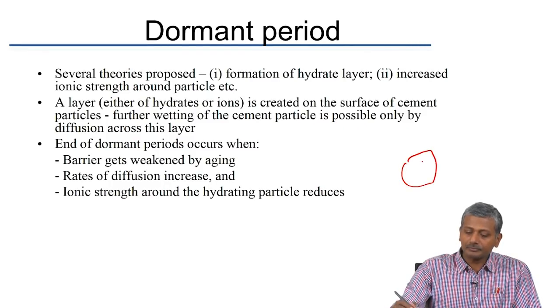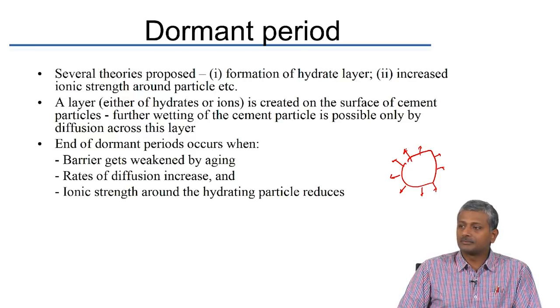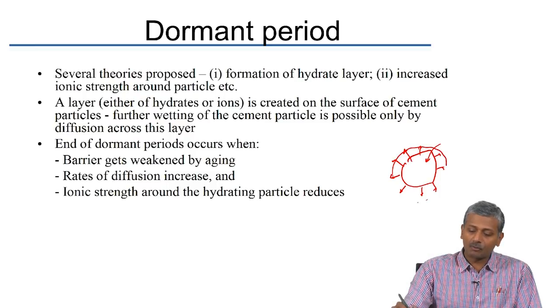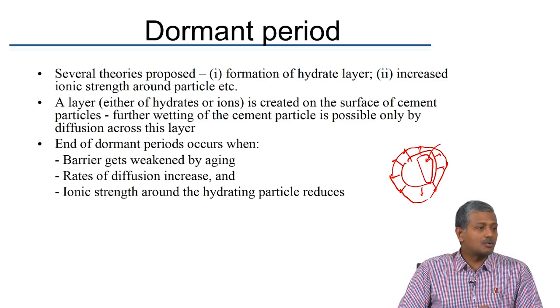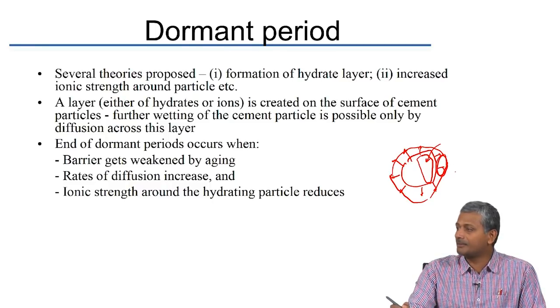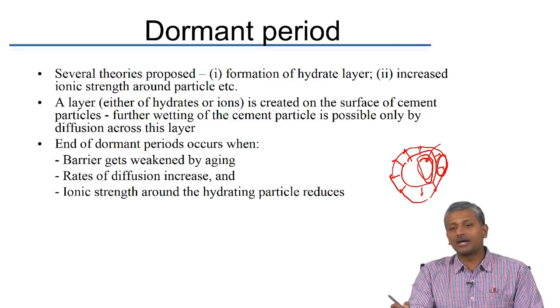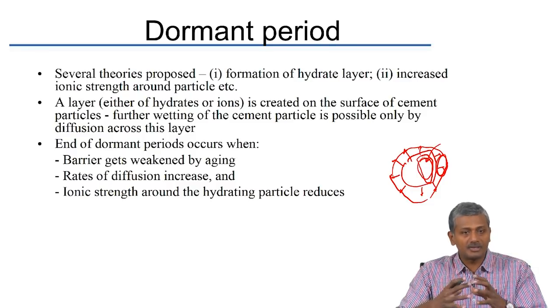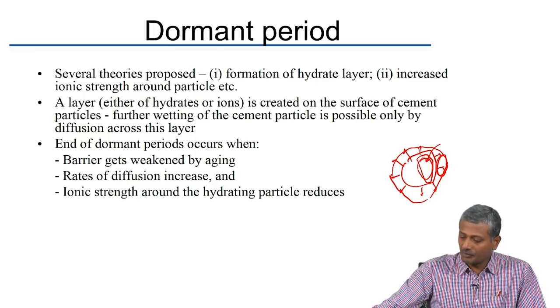There is a specific mechanism of cement-water interaction. Initially there is dissolution of ions from the cement particle outward. Later, water diffuses through the initial hydrate layer forming on the surface and then interacts with the particle in its location. This leads to two types of CSH: outer CSH that forms outside the cement grain due to dissolution, and inner CSH that forms inside the cement grain due to inward diffusion of water.